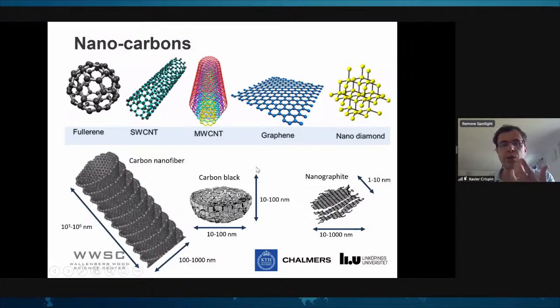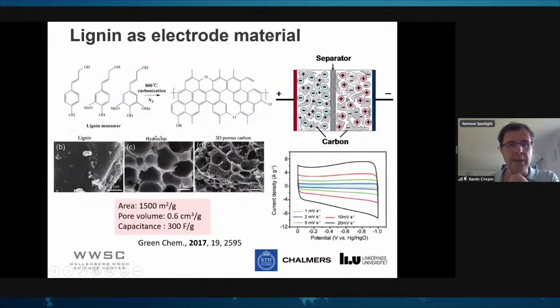All right. So one of the things that people have been doing is to use lignin as electrode material by carbonization. So basically, you heat lignin in nitrogen to almost 1,000 degrees and form aromatic rings, and you form, step by step, structures that start to conduct electricity because they're aromatic. So you have graphene sheets and graphitic planes that are formed.